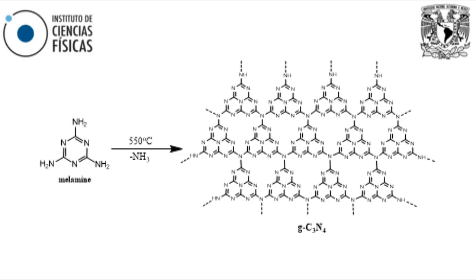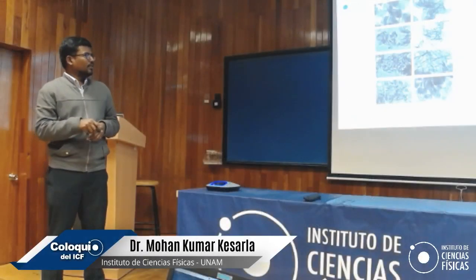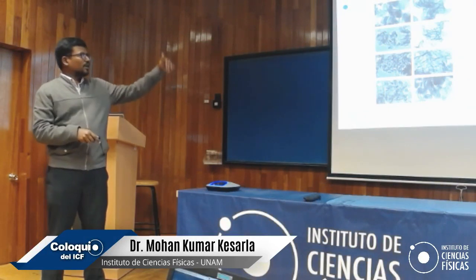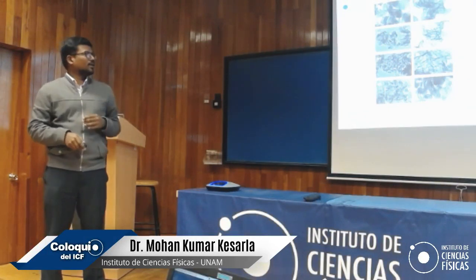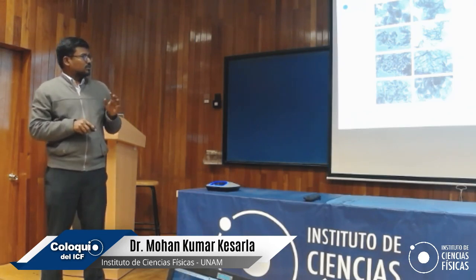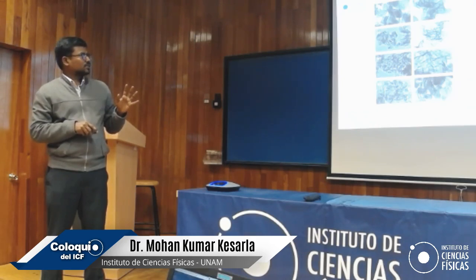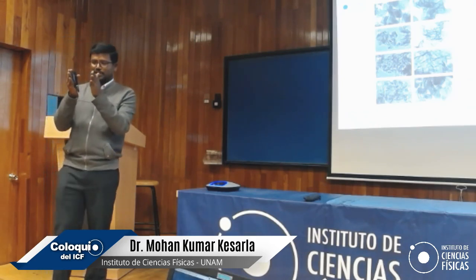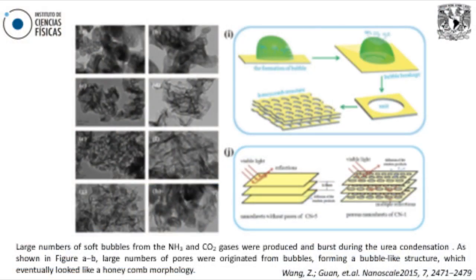But there are a lot of modifications on graphitic carbon nitride. If it is bulk graphitic carbon nitride with a surface which is not porous, what will happen? Visible light comes and many reflections will be there. So they created pores on these layers. So this is a close-packed layer, and we can exfoliate it to get monolayers also.